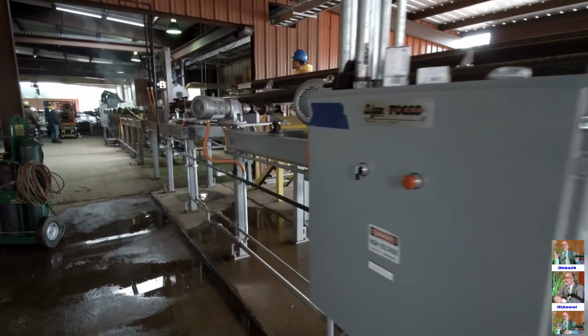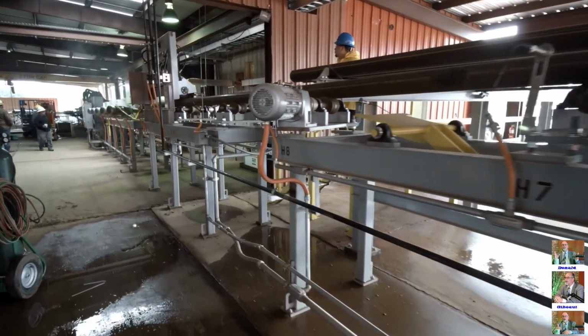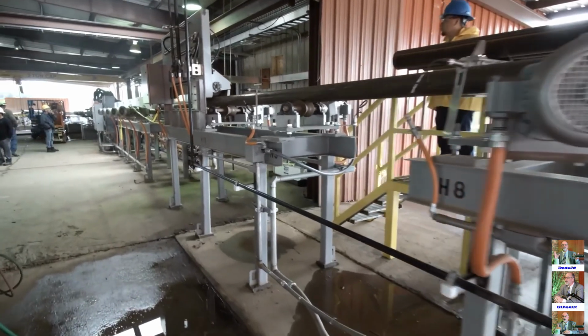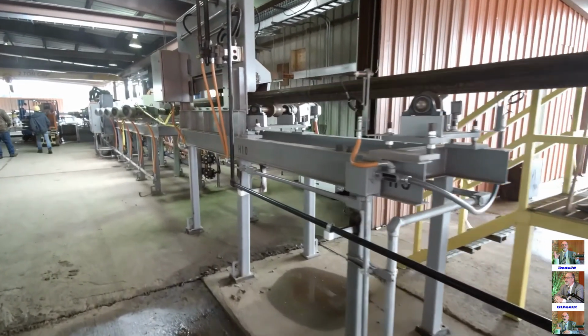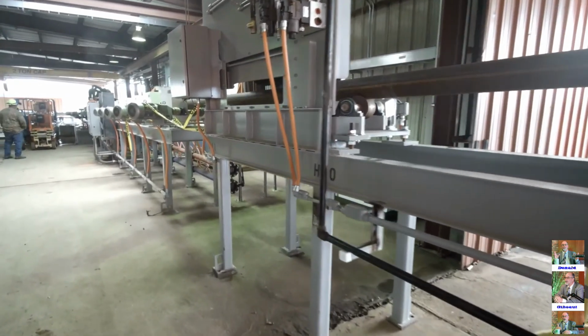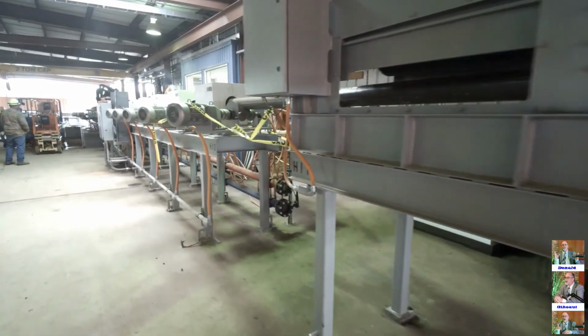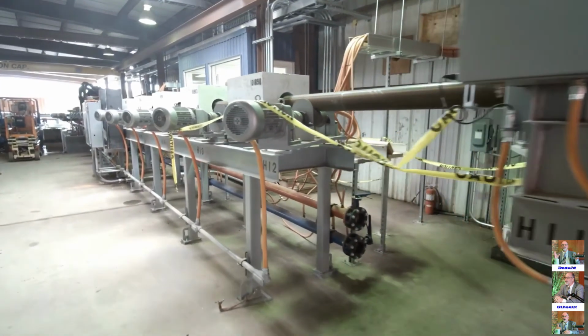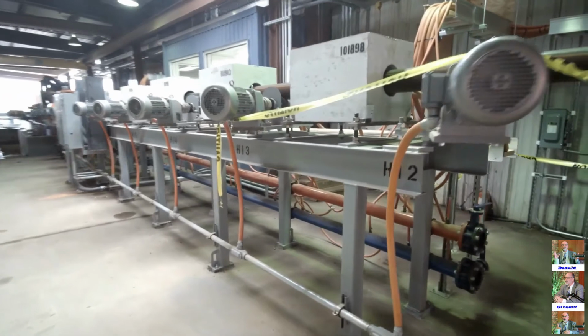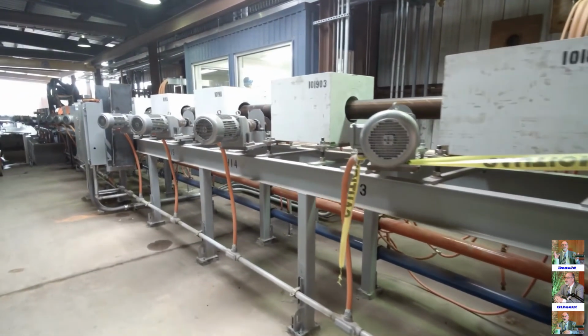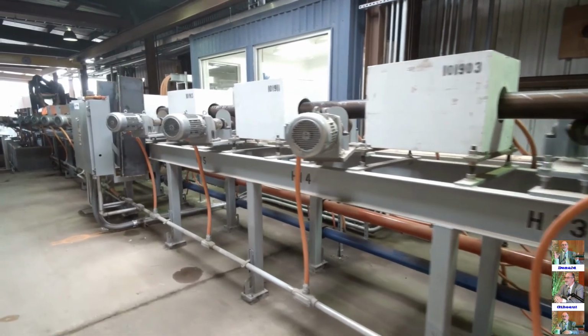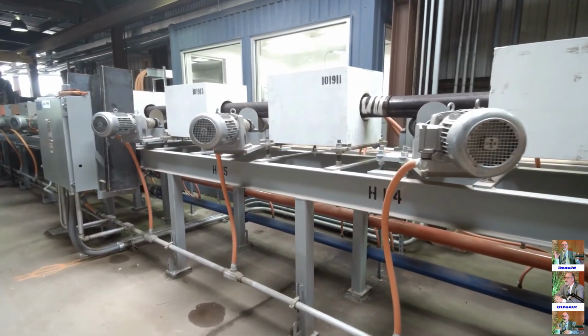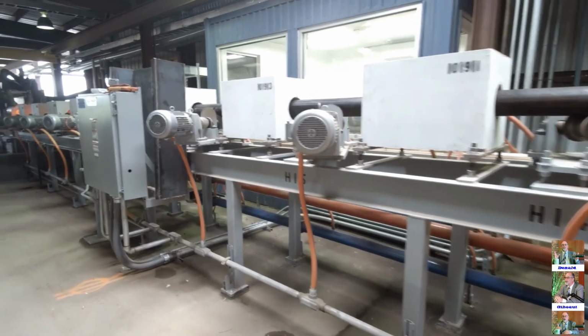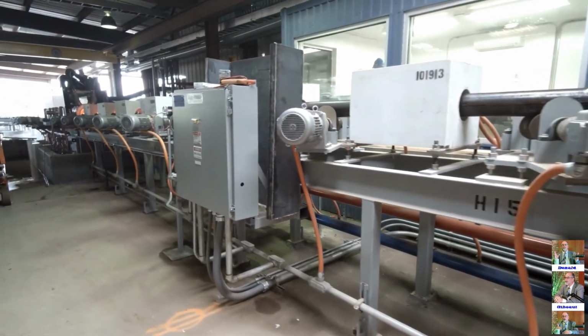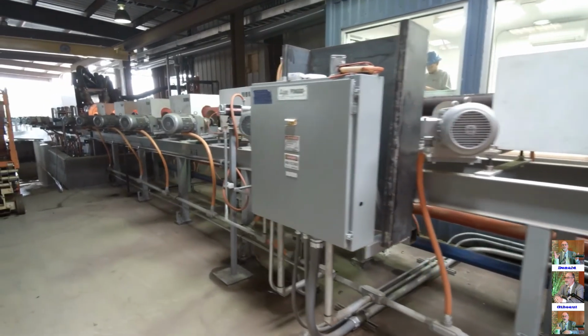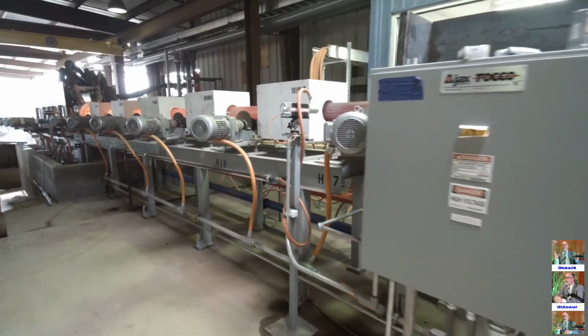The centers between these rolls are about 5 foot. You can see photo eyes there to the right that identifies the front and the back of the tube, so we can, in the controls, keep them butted. This mechanism here is a brush for rusted pipe that comes in off the yard. Now we stop the line here so you can see the butting of the pipe together. Here in about the third coil you can see it there. It's very nicely butted together, which is important so we don't get into the current crowding that we discussed earlier and overheat the ends.